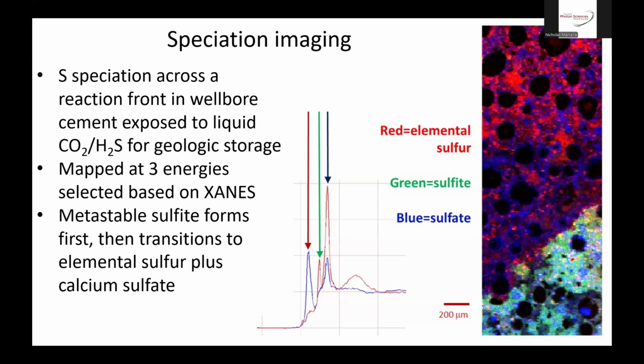So as the reaction progressed through the cement, it initially formed a sulfite, which was a metastable intermediate, and then that reacted further to form calcium sulfate and elemental sulfur, which is more stable long term. So again, this is just repeating the same map at three energies and then calculating out the results based on what we know about the XANES. So we can map different species that way. And I've done similar work with up to 5 different sulfur species, relative distributions in a complex sample. So it's pretty useful.